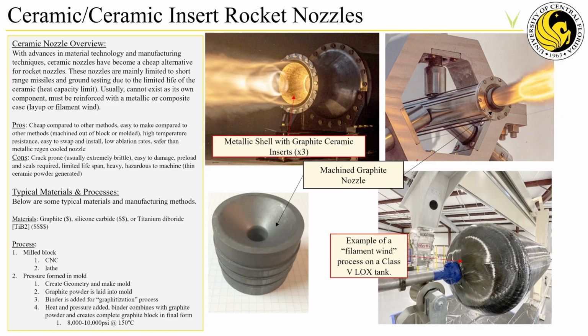Now, the problem with these types of ceramic nozzles is that they're quite fragile and they're prone to cracking. If you have a nozzle crack, you increase surface area and then you lose pressure, and you get a whole host of other problems, and then you have a leak path that makes its way to the outer casing, and you're going to melt your outer casing, and then the whole thing falls apart. So there are a lot of issues with ceramic inserts due to cracking or even having interfaces between the ceramic plates. And mounting these types of ceramic nozzles is actually quite difficult as well.